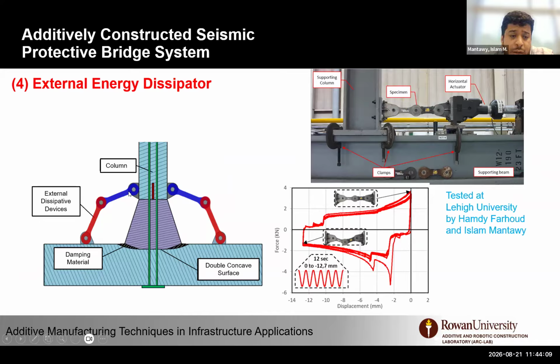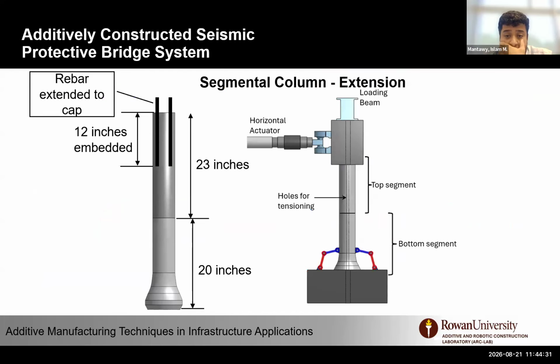As of now, we can also take away the external element and tune those cavities and material to damp the desired motion. By doing so, we also shift the system to be seismically isolated, because we are going to reduce the demand as the system becomes a little more flexible. So the acceleration will drop, and therefore the demand will be lower. We are in a phase of testing this idea at Lehigh University in the fall.